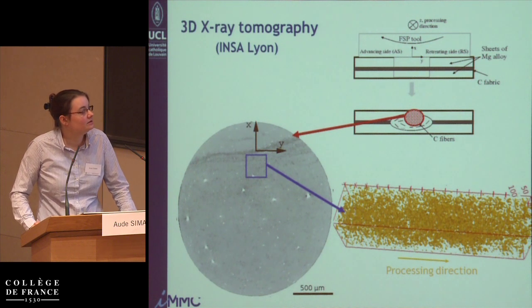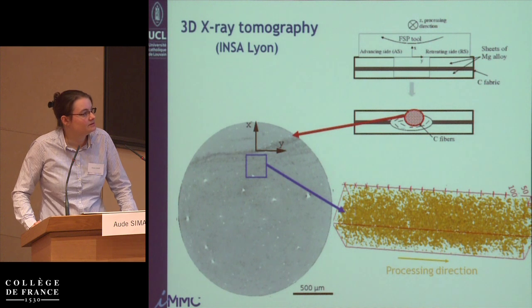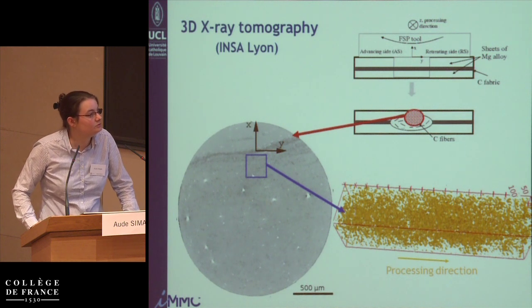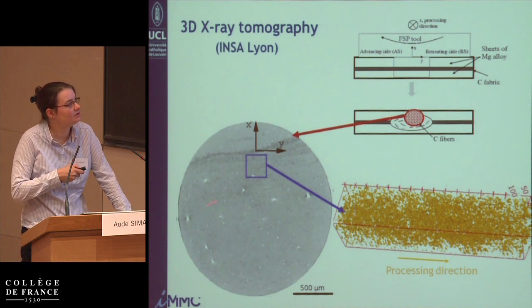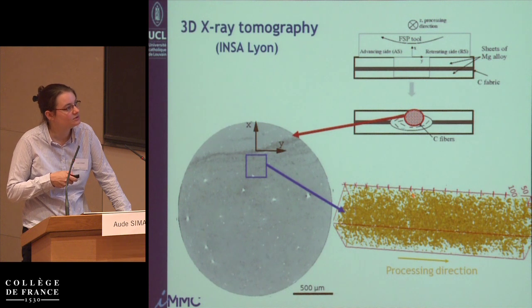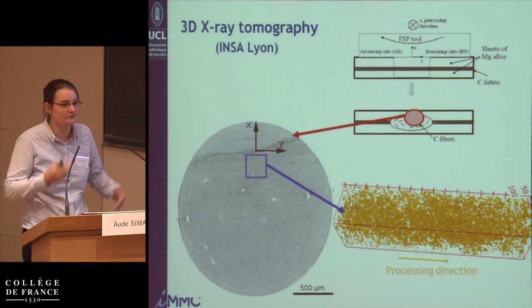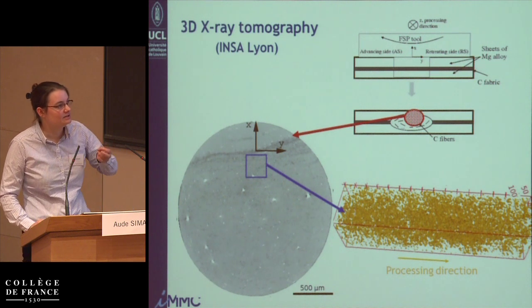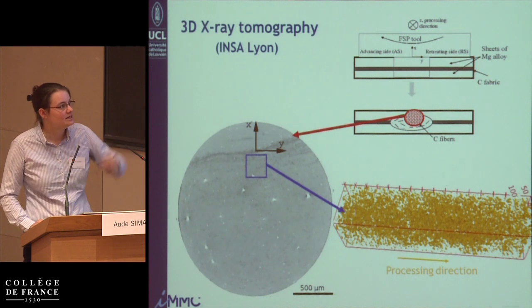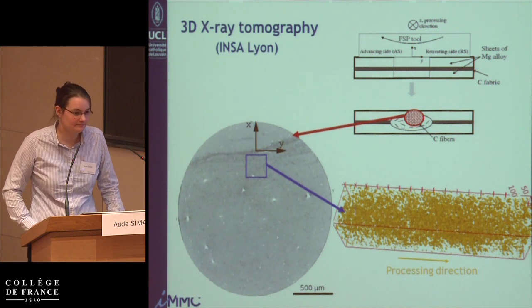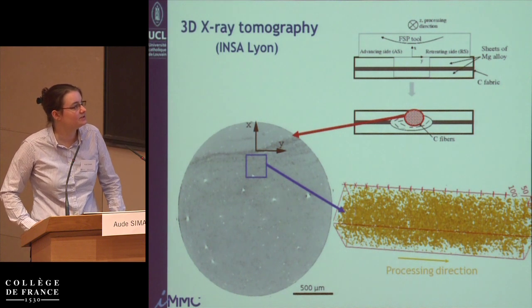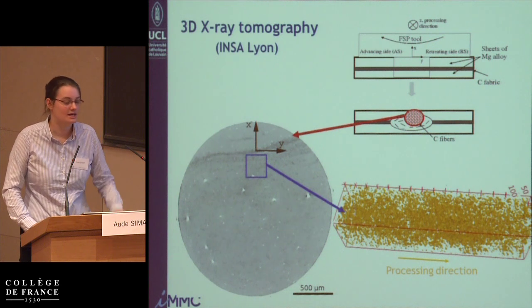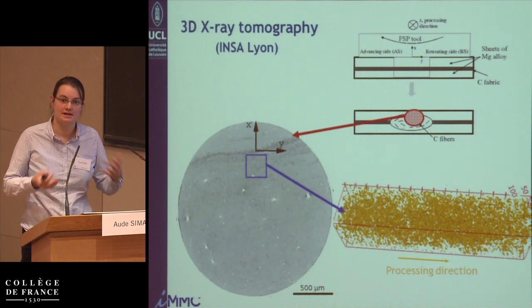And these experiments were performed at INSA Lyon by Jérôme Adrien and Eric Maire. And so we analyzed at Université catholique de Louvain these results and could extract different boxes, let's say, where you can have the fibers here. And so here it's very difficult to see, because you have a lot of them, but there are fibers that have various orientations in this box, and you can see them in 3 dimensions, and so obtain orientations, length, and so forth.